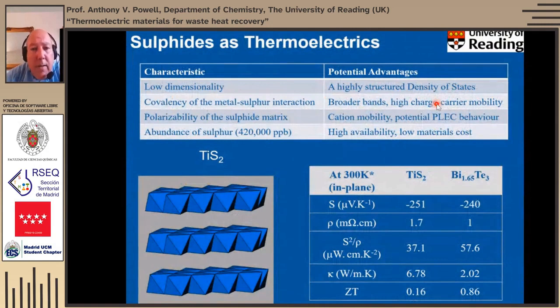In terms of the rest of the talk, I'm really going to focus on sulfides. And what I'd like to do is just very briefly say why sulfides have attractive features. Many of them, including TiS2 that's shown here, are low dimensional, so that gives them a very highly structured density of states. The metal-sulfur interaction is quite covalent, so that means that we're going to get broader bands and higher carrier mobilities. It's also very polarizable as an anion matrix, so that means that we're going to see significant cation mobility and potential for phonon-liquid electron-crystal behavior.